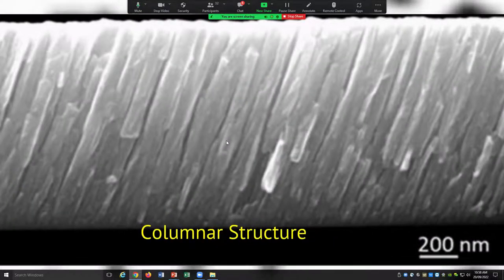So you can see the porosity's gone. You've still got this sort of structure in there and the atoms are still coming in, landing and sticking on each other, and they build a columnar structure. But it's a lot denser. You don't see those large voids or large pores. And for certain situations, this is fine. Probably an amorphous coating as well, and quite adequate for a lot of applications.